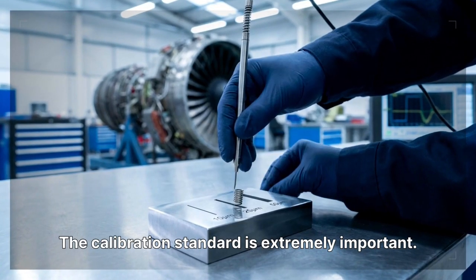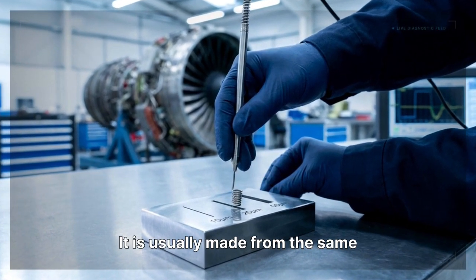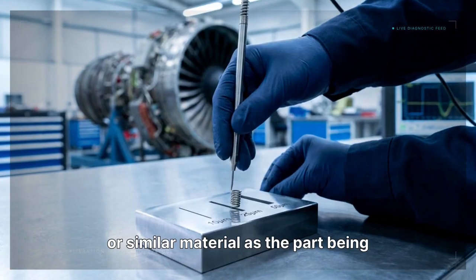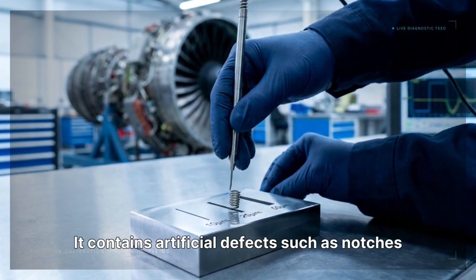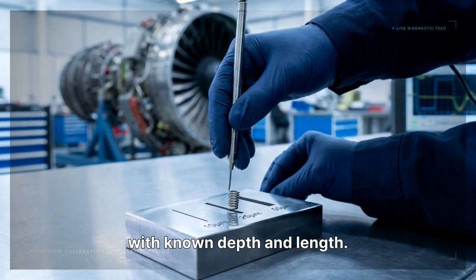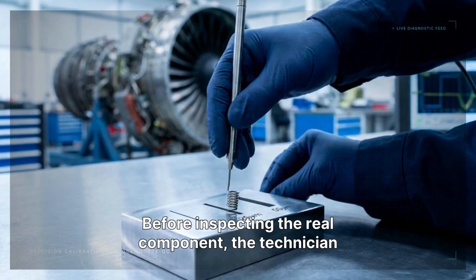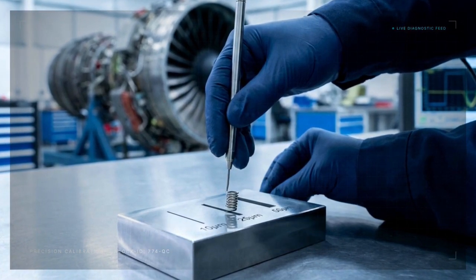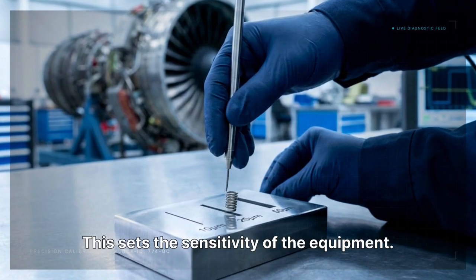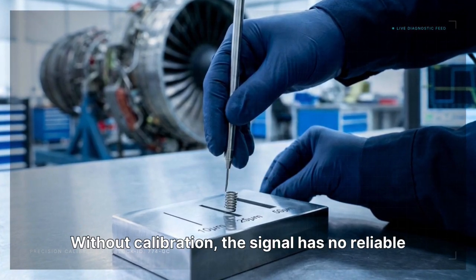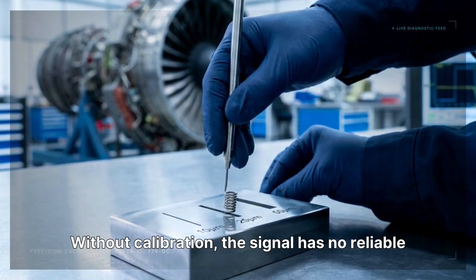The calibration standard is extremely important. It is usually made from the same or similar material as the part being inspected. It contains artificial defects, such as notches with known depth and length. Before inspecting the real component, the technician scans the calibration standard. This sets the sensitivity of the equipment. Without calibration, the signal has no reliable meaning.